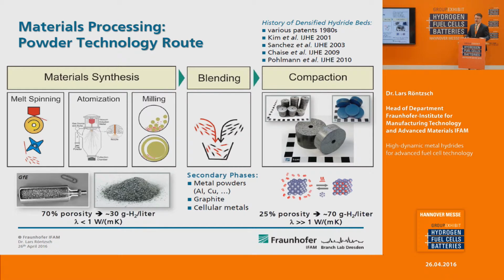Therefore, usually secondary phases are added to the hydrogen storage material, materials like graphite or aluminum that have intrinsically a very high heat conductivity are added to the hydride forming powder. A mixture is being created and then in a uniaxial compaction one would end up with these pellet-like forms, a cylinder usually is used. And these pellets then are introduced into the pressure vessel where the hydrogen storage takes place.